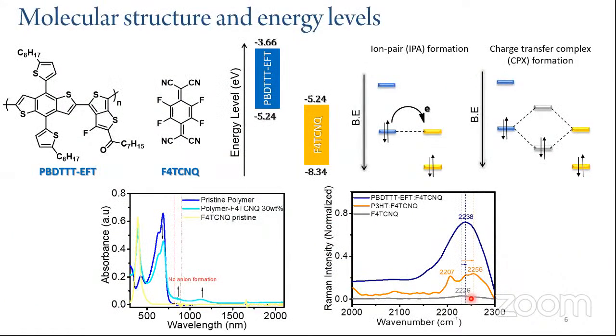So with this insight, we come to our work, where we have used the semiconductor PBDTTT-EFT, which is a conjugated push-pull polymer based on a benzodithiophene-based donor and thienothiophene acceptor, and it is doped by a strong acceptor, that is tetrafluorotetracyanoquinodimethane, that is F4TCNQ. The energy levels of the polymer and the dopant are such that efficient electron transfer from the HOMO of the polymer to the LUMO of the dopant is feasible.